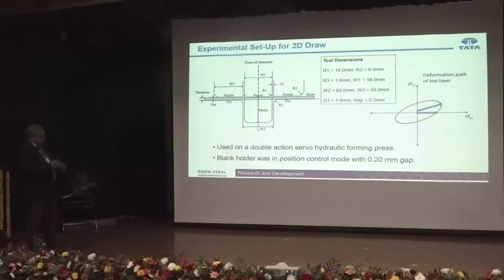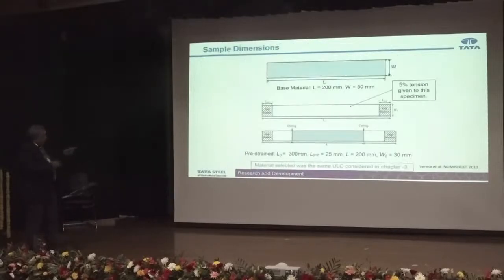What we did is, we added a little bit of complexity to that. We took samples, and this was the base material. We did some experiments only with the base material, which was fully annealed samples. Then we also took this material and gave it some pre-strain. We did some tensile deformation, about 5%, and then we made samples from the center and did the 2D draw.